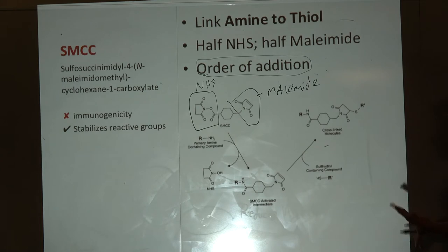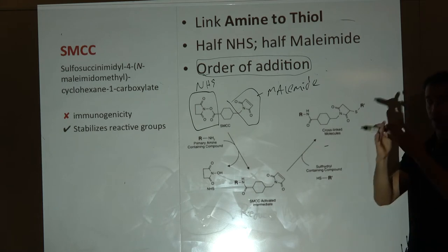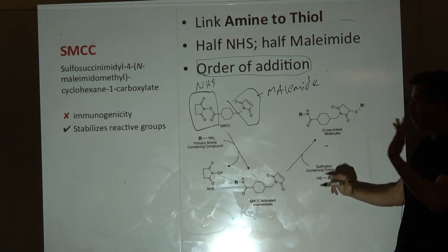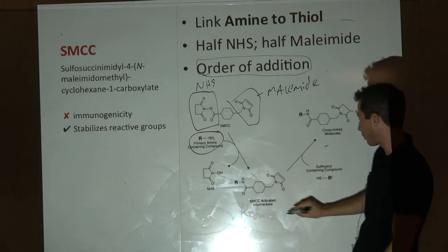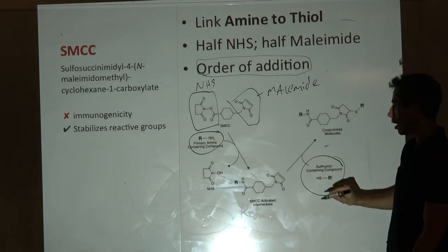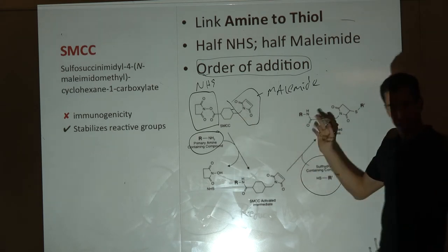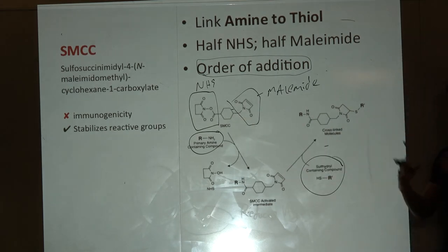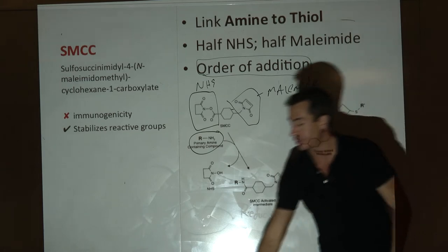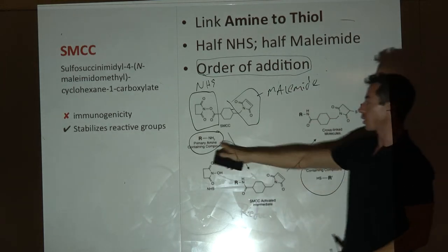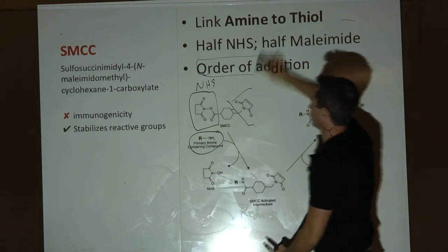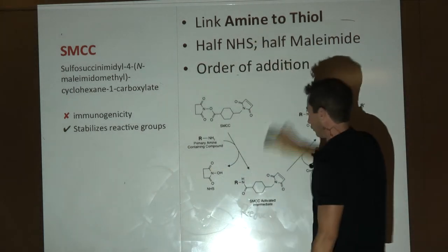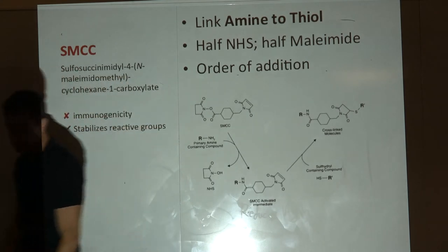Sometimes you want to react with your amine, then purify, then do the reaction with the maleimide. This is much less stable than maleimide, so you'd always want to react with your NHS group first. A lot of times you can add everything in the same pot, but if it doesn't work, do it sequentially with the primary amine component first.